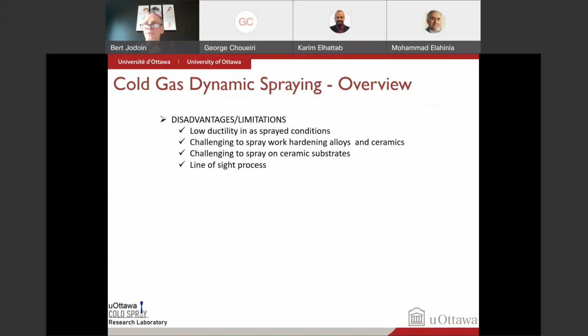And it's a line of sight process. So it means, right, you're scanning, so you can only spray what you can see. You cannot spray behind things. You can only build up on top of things. So that's also a major limitation. And spatial resolution is also limited. I mean, you can shrink the nozzle size, but up to a limit. So the resolution is probably 25 to 30 microns at best. So that's also a major limitation.